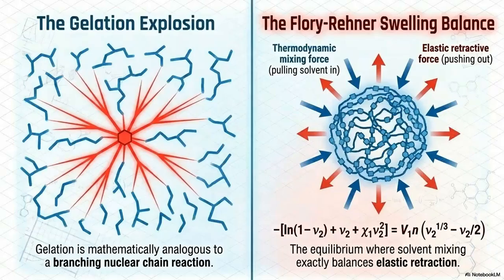This slide illustrates two breakthroughs in polymer physics. On the left, the gelation explosion shows that gelation is mathematically analogous to a branching nuclear chain reaction, where a sudden network expansion occurs. On the right, the Flory-Rehner swelling balance defines the equilibrium state of a cross-linked polymer network in a solvent.